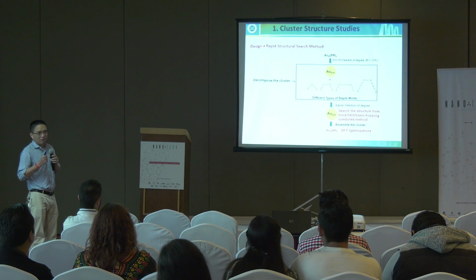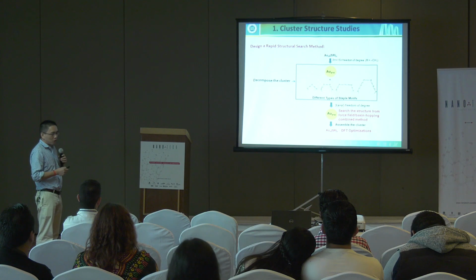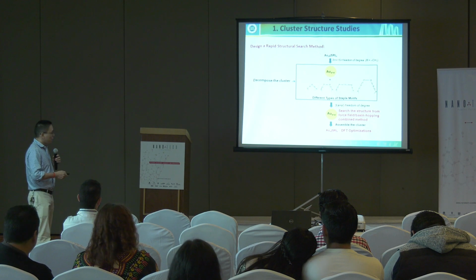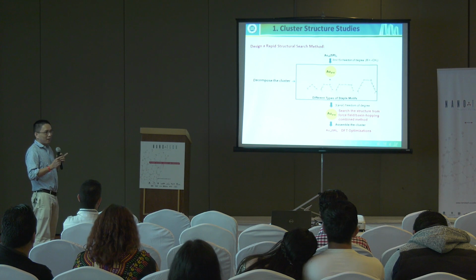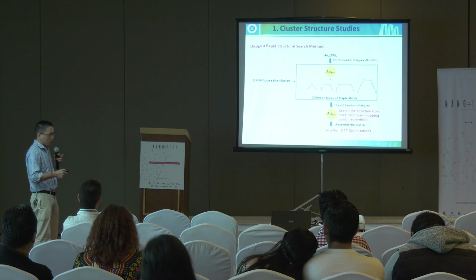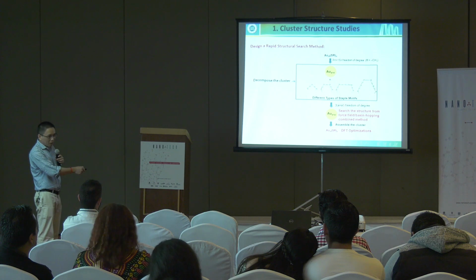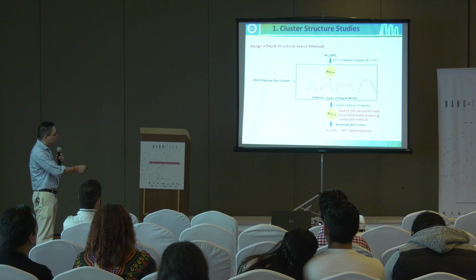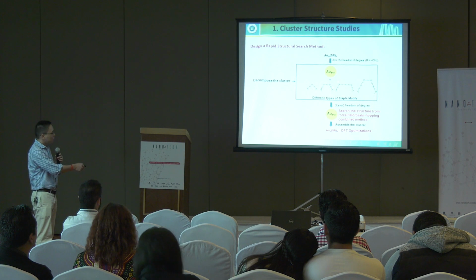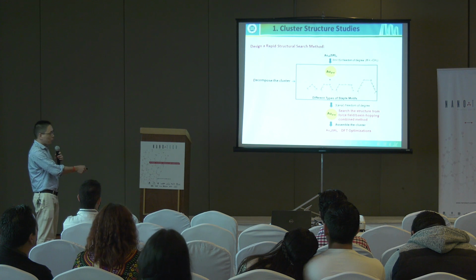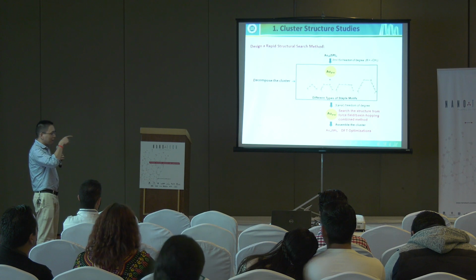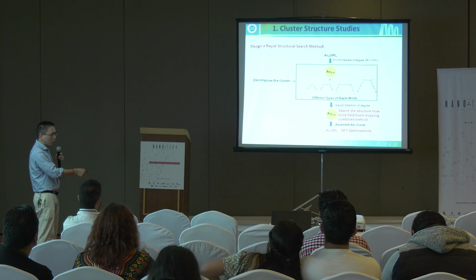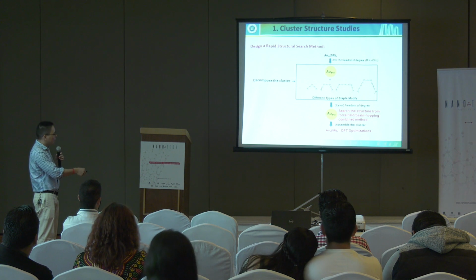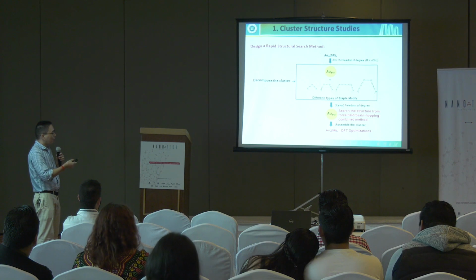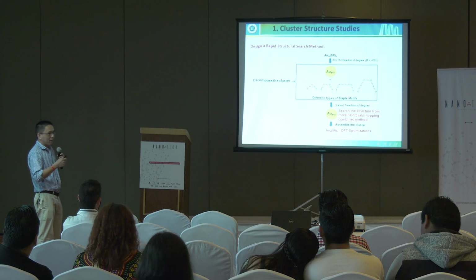Based on this structure formula, we can devise an efficient theoretical method to explore the cluster structure. So we do not need to consider the ligand effect during the structure search. Why? Because according to the structure formula, we can divide any cluster into a metal core and a certain number of already known motifs. So what we should do is carry out a structure search for the metal core. And after that, we put these motifs on the surface of the metal core to assemble a cluster, and then we use DFT calculations to do geometry optimization, and then we rank their energy orders.